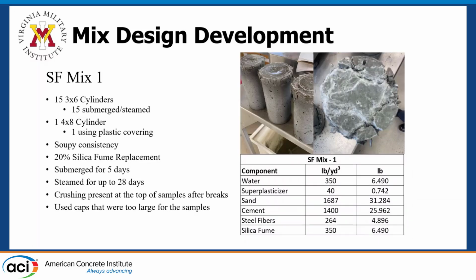So going on, here's our first mix with silica fume. 15 3x6 cylinders, all submerged as steamed. We had 1 4x8 cylinder for later testing. We actually used a 20% silica fume replacement. So we found a soupy consistency. The water itself was low, but it left behind residue. And that presented a ton of problems. However, the strength itself, as you'll see later on, could have been a lot higher.